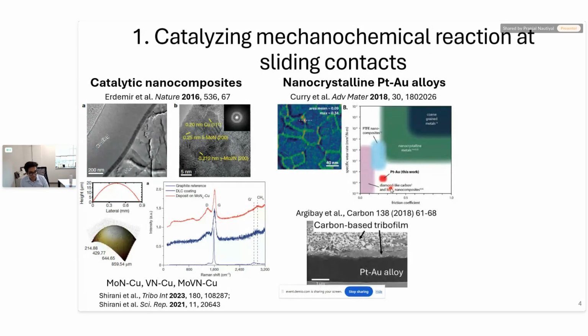Later studies by this group showed that these platinum-gold alloys were also inducing a carbon-based tribofilm formation. So here I'm showing you the platinum-gold alloy. The tribology test was conducted, and at the end of the test, they observed the formation of a nanocomposite film, which was composed of carbon combined with some wear debris. And there have been a lot of studies on this system in recent years from Sandia, as well as Professor Filippo Mangolini's group at UT Austin.